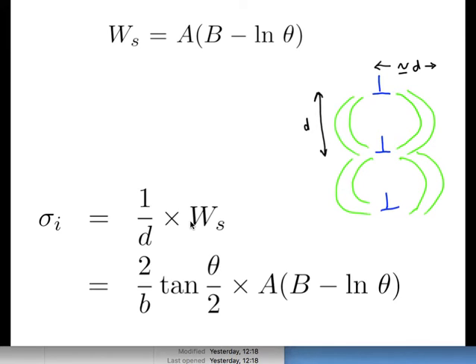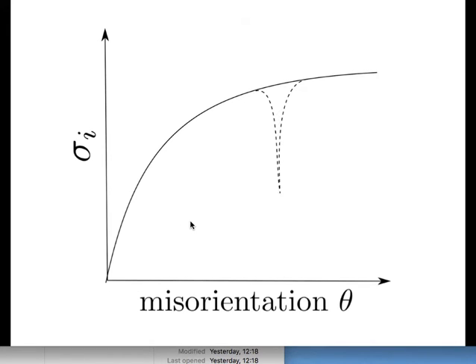So this is called the Read equation, and if I plot it, it looks like this. So ignore the dashed line for the moment. The interfacial energy increases continuously as a function of the misorientation theta. And any idea why the slope is decreasing? The physical reason, okay? Obviously, the equation gives you that. It's basically because as they get closer and closer together, their strain fields are becoming vanishingly small, okay? Only the core energy becomes important.